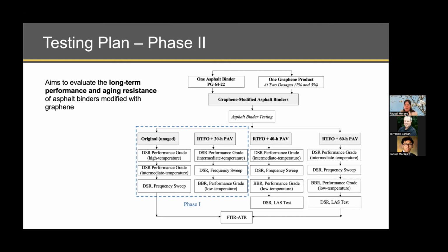So with that in mind, we would like to see how these blends perform in terms of rheological properties after they are subjected to 40 hours and 60 hours of PAV aging with the additives. And after these binders are aged in these 2 extreme aging protocols, we would measure the rheological properties of the binders in terms of performance grading, exactly what was mentioned today. What would be the effect after long-term aging of the specific additives when considering low temperature cracking, for example, and also intermediate temperature cracking, incorporating more advanced testing protocols than what's presented today. So this is what we are targeting with phase 2 evaluation.